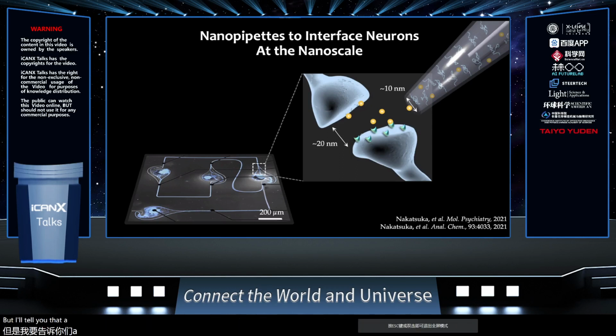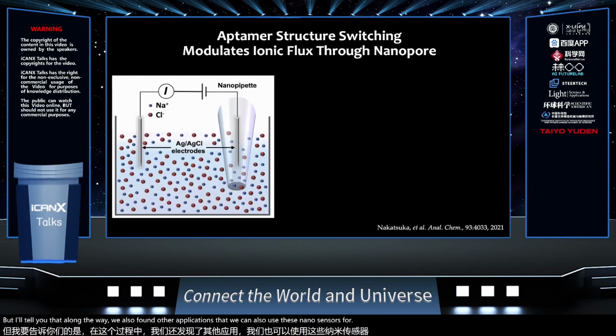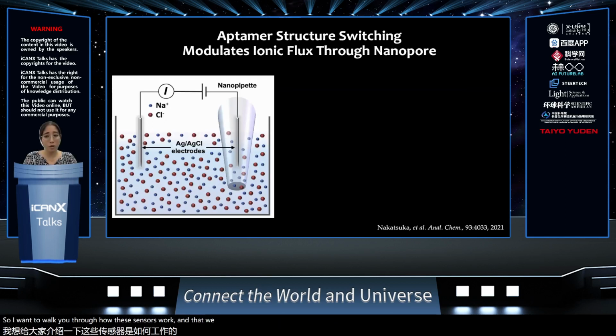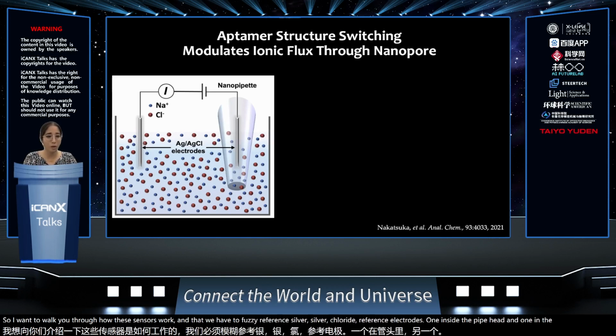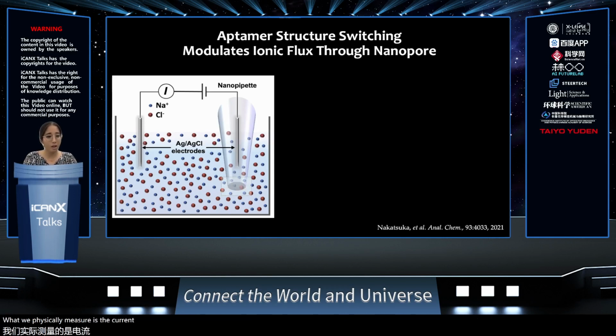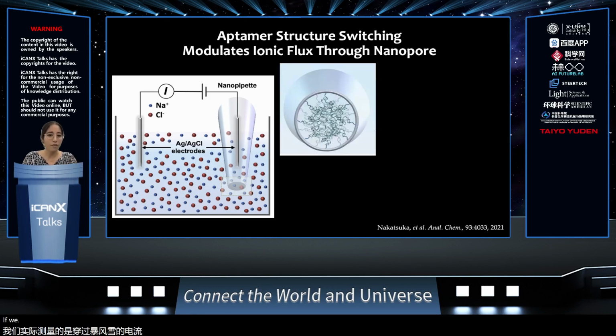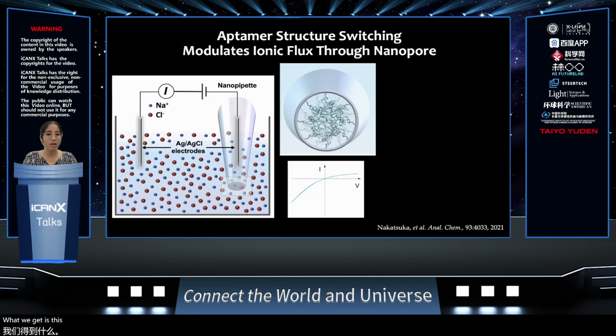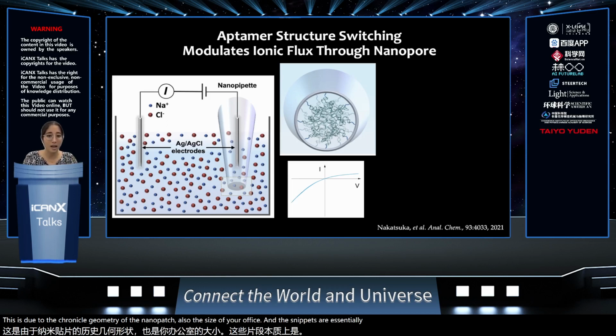But I'll tell you that along the way, we also found other applications that we can also use these nanosensors for. So I want to walk you through how these sensors work, and that we have two quasi-reference silver-silver chloride reference electrodes, one inside the pipette and one in the bulk solution. What we physically measure is the current that goes through this nanopore. If we modify the inside of this nanopore chemically with these DNA aptamers, what we get is this ion current rectification event. It's basically a non-linear behavior in the current response when applying a linear voltage. This is due to the conical geometry of the nanopipette, also the size of the orifice, and the surface charge density inside of this nanopore.